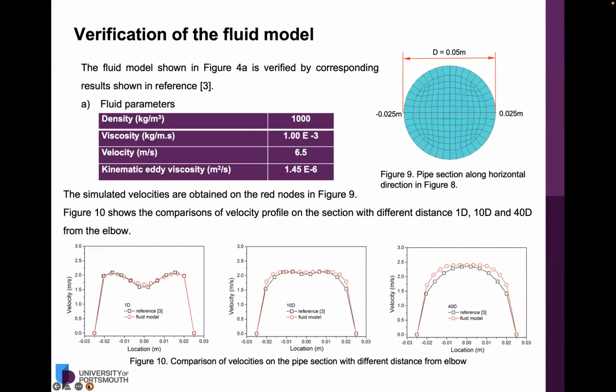So we run the FSI simulations and the result are verified again using the published data. This time is reference 3. The details of these references are in the final slides of this presentation. So what we are trying to show here are the profile of velocity against locations, and the locations are along this diameter of the cross-section of the pipe. And this is referred to the distance with respect to the diameter. So this is 1 times diameter, 10 times diameter, 40 times diameter distance from the elbow. Again, it shows that our fluid model are more or less in agreement with the reference data published in the journal.